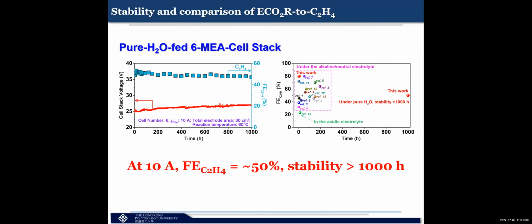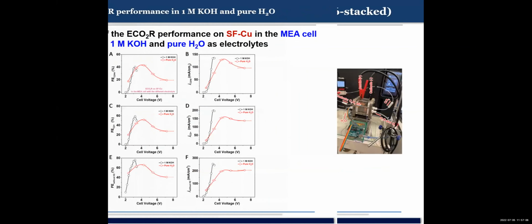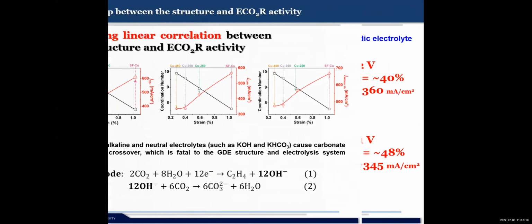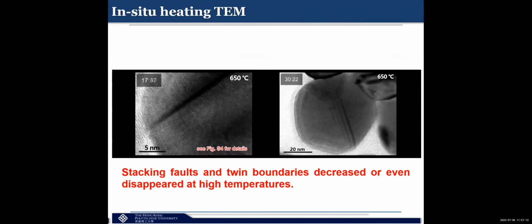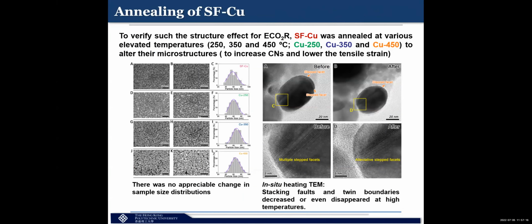Professor Lau, in one of your slides, you showed the in-situ heating TEM experiment, and after heating, you can see the particle size decrease significantly. Here? No, the particle size did not really decrease. If you look at the anneal at 450 degrees, the size is still about 60. No, I mean in your TEM, if you compare A and B, right? I think it's about the focusing. It's not exactly about the actual size. Yeah, because the focusing is not the same, because of the drift.